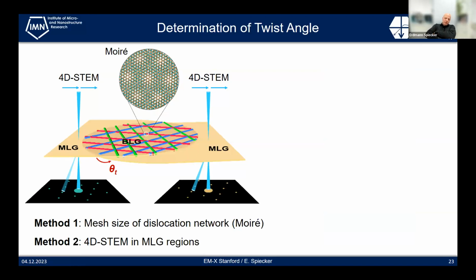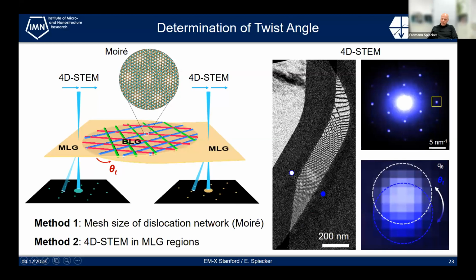Okay, now how can we evaluate the twist angle? This is pretty straightforward. There are 2 ways to do that. Either we just rely on the density and the mesh size of the dislocation network, or the moiré, so to speak, or we evaluate with 4D STEM, on the left and on the right side in the monolayer graphene region, the relative orientation of the diffraction patterns. And actually, this is shown here, where we measure on the left and on the right of, for example, this area here, and we see that there is a rotational shift of the diffraction spot here, which we can measure and determine the twist angle locally. So you see that the twist angle changes from bottom to top, because also the mesh size changes from bottom to top.